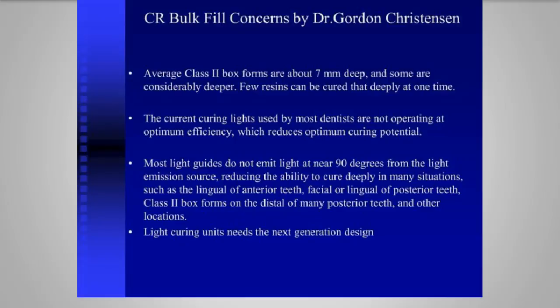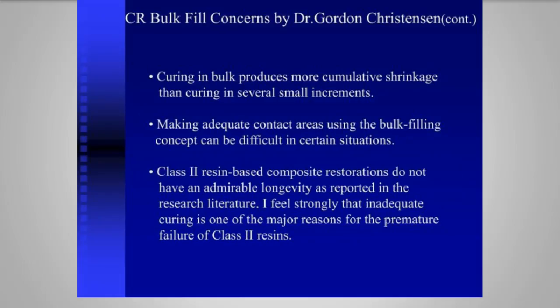If you look at most lights, they don't emit at 90 degrees from the emission source. And so you're inefficient as you go into different anatomical areas, such as the lingual of anterior teeth, facial or lingual of posterior teeth, and the distal box, especially when you get into a distal extension box and you're chasing decay around the lingual side. You don't know where the light is. Can it get down there? Which begs the point of getting better curing lights. There are a lot of good curing lights in the marketplace today, but the point is make sure you're using a decent curing light that's being tested and clinically performs correctly.